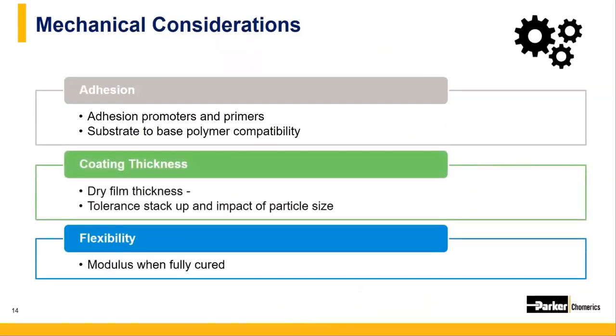Adhesion strength is important to consider because not all polymer binder systems will adhere well to various substrates. Oftentimes, surfaces must be prepared with primers, adhesion promoters, or physical and chemical etching that we will discuss in more detail later in the webinar. Yeah, and Ben, I'd like to add a word of caution on that note. When you consider using a chemically resistant plastic, that means that the plastic will resist the chemical coating. So I've seen these parts get sprayed and then literally the paint is dripping off and not adhering.